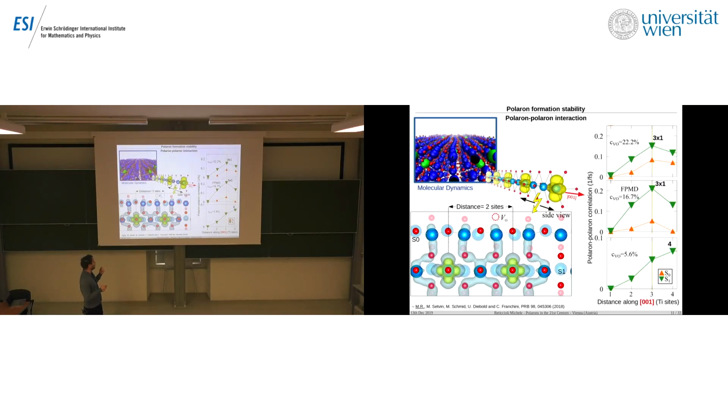That would determine a strong interaction of polarons, but actually this peak stays here, and what happens is that polarons start to populate more and more often the surface layer. So the density in the subsurface layer stays fixed at 1 polaron every 3 lattice sites, which we call a 3x1 pattern, such that they do not overlap much.